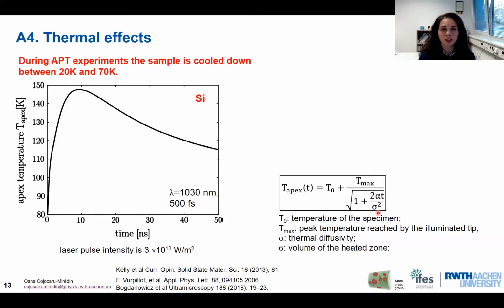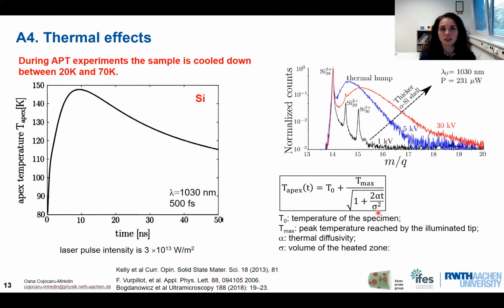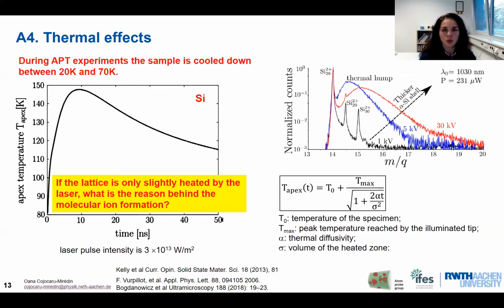So that means actually that the work that I have shown you before, that the formation of molecular ions is due to the melting temperature, cannot be the reason for the experiments where we see molecular ions using modern atom probe tomography. Of course, we have some thermal effects, and this we see very nicely in mass spectra of the silicon tips, where we have this thermal tail on the mass spectra, and these thermal tails are sometimes impossible to avoid. So if the lattice is only slightly heated by the laser, then what is really the reason behind the molecular ion formation? But before speaking about that,